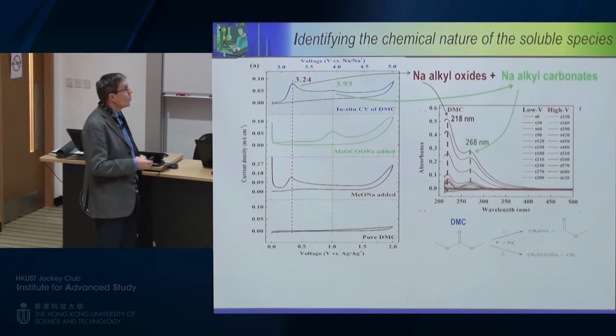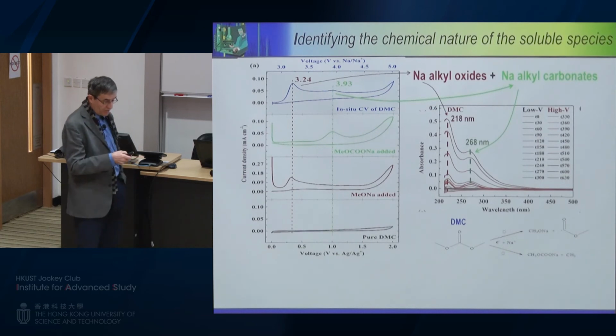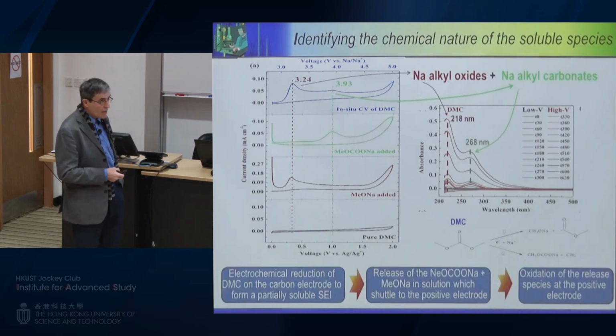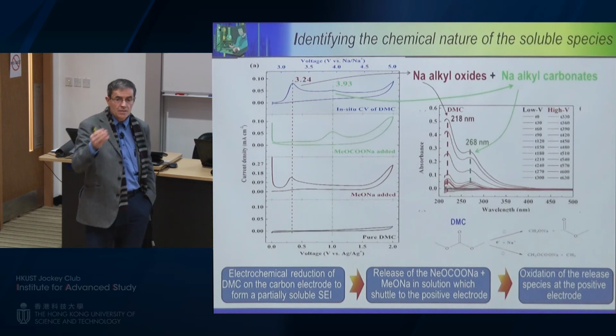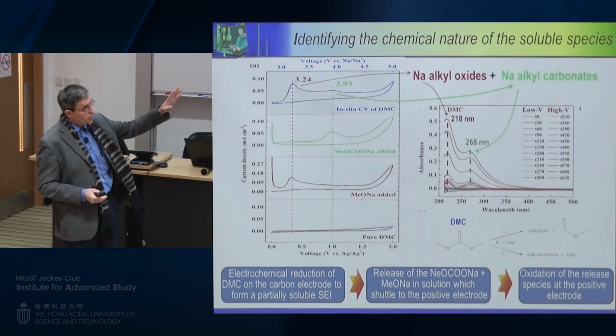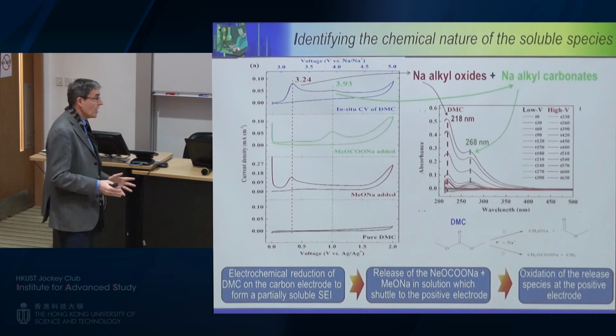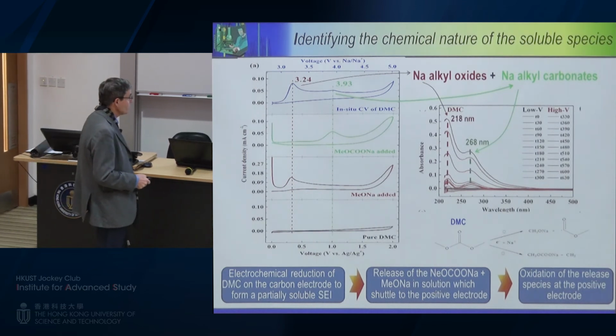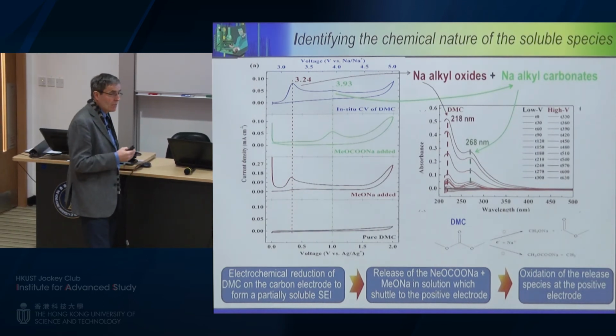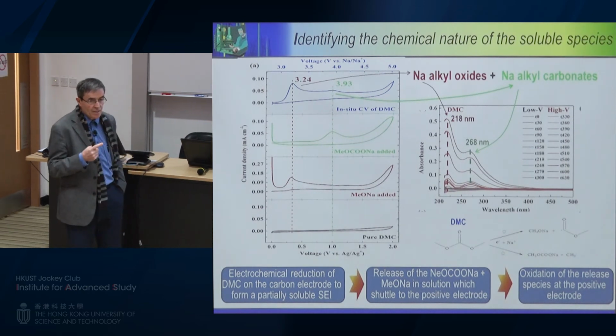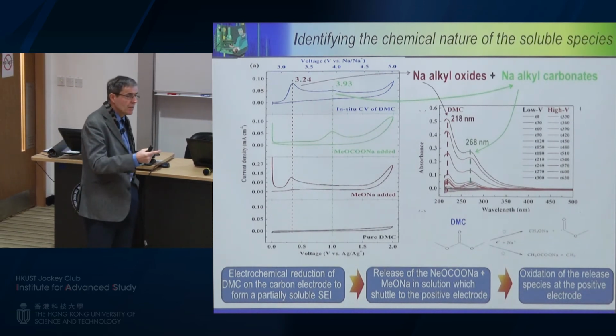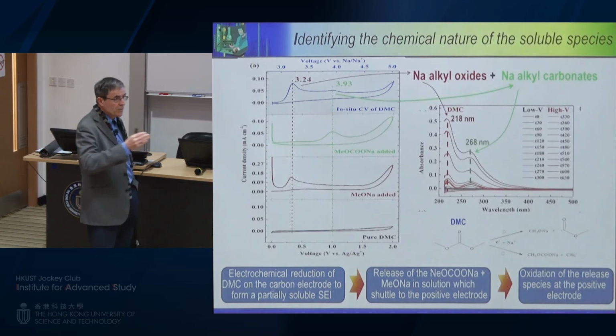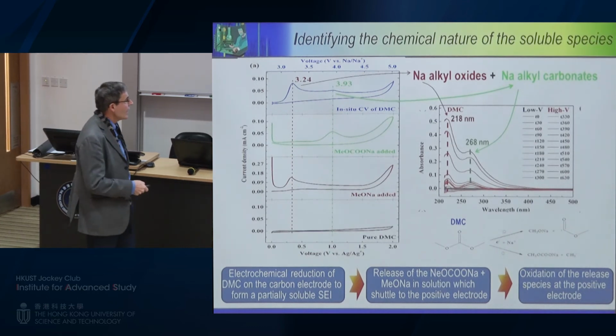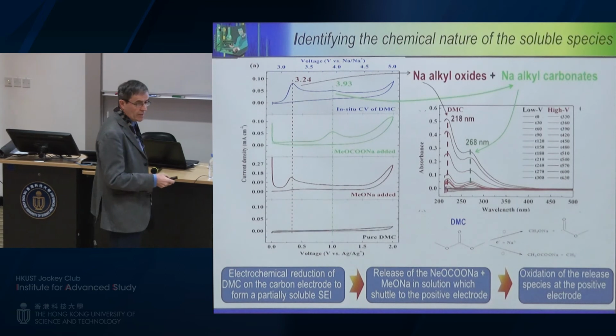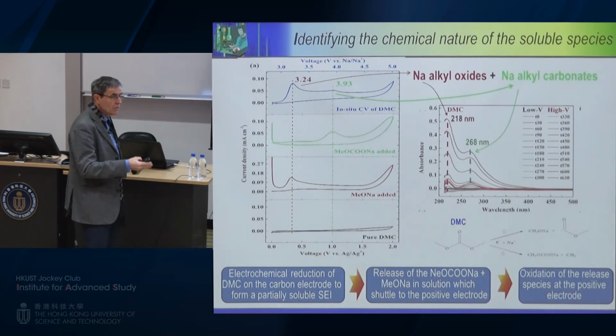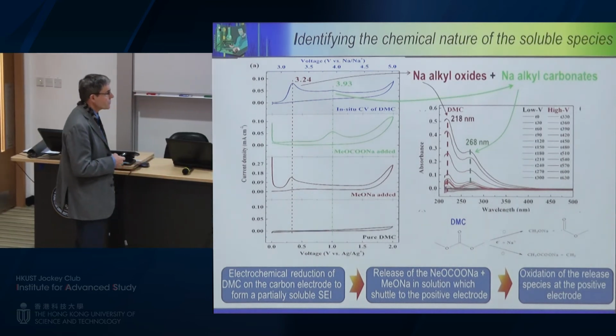So now, we know what is happening in these cells, which means that when we are in this kind of EC DMC based electrolyte, the EC is safe, the DMC is a disaster, because it's going to be reduced at the carbon electrode to create an SEI, but which, in contrast to lithium ion, this SEI is not stable, it's going to dissolve, it's going to release species, and these species are going to be oxidized at the positive electrode. So this is really the problem that we have.